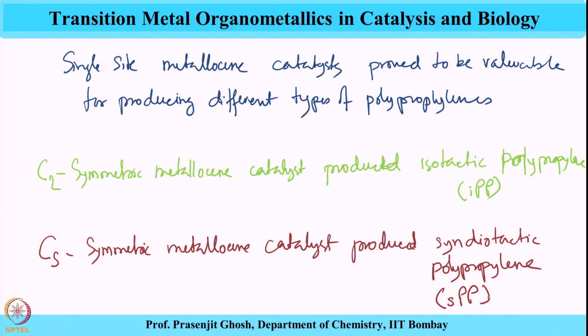The top one showed incorporation of polymer through one particular face of the propylene, whereas the bottom one showed incorporation of propylene alternating between two different faces of the propylene. So, with this we come to an end of today's lecture, where we had seen the effect of C2 symmetry in producing isotactic polymer, as well as a nice work by Ewen, which showed the effect of CS symmetry producing alternating syndiotactic polymers. Syndiotactic polymers are more soft, more ductile and transparent than isotactic polymers, and have relevant application